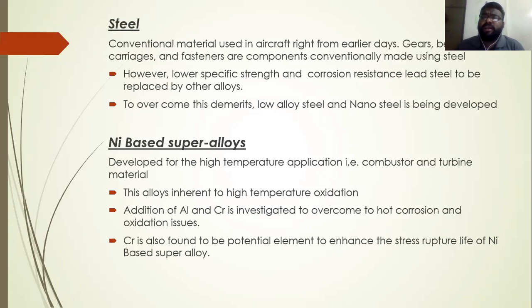Possible solutions are low alloy steel, which is currently under research, and nano steels being developed to address these issues. And similarly, nickel-based superalloy. We are talking about increasing the operating temperature of the material, and this is one of the important materials which can be used for enhancing the performance of the engines. But this alloy also has a problem, which is high temperature oxidation. Because it is exposed to high temperature, the material is prone to oxidation, and this problem should be addressed. Currently, people are adding chromium or aluminum to this superalloy to increase the resistance towards high temperature oxidation. Chromium is also found to be a potential element to enhance the stress rupture life of the nickel-based superalloy. So by alloying, this problem could be faced effectively.